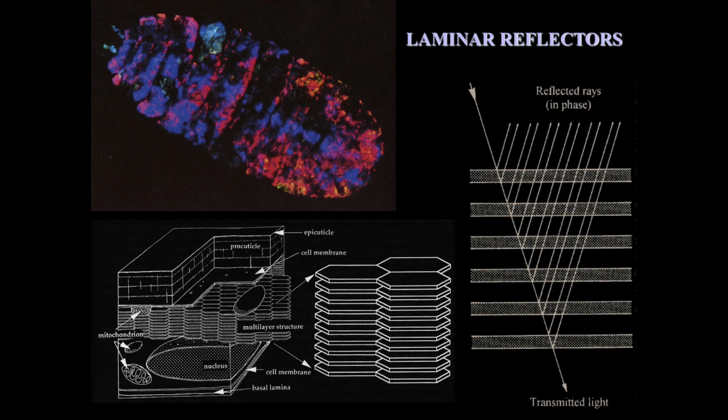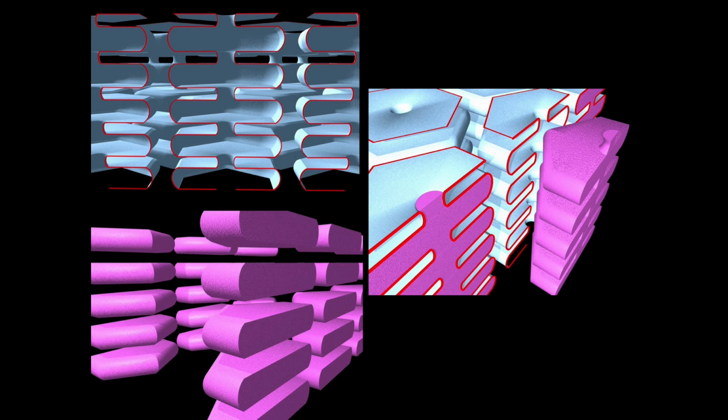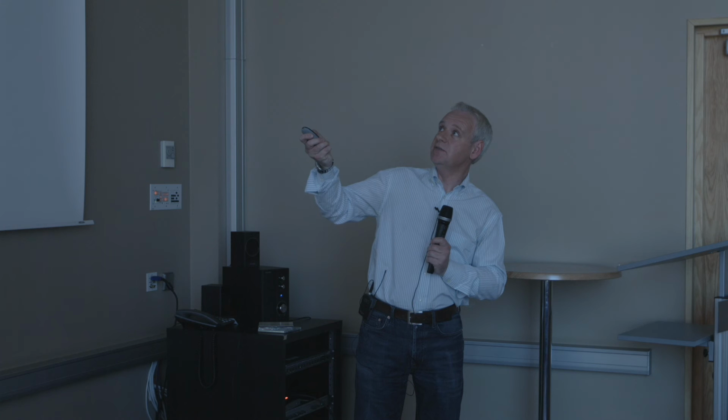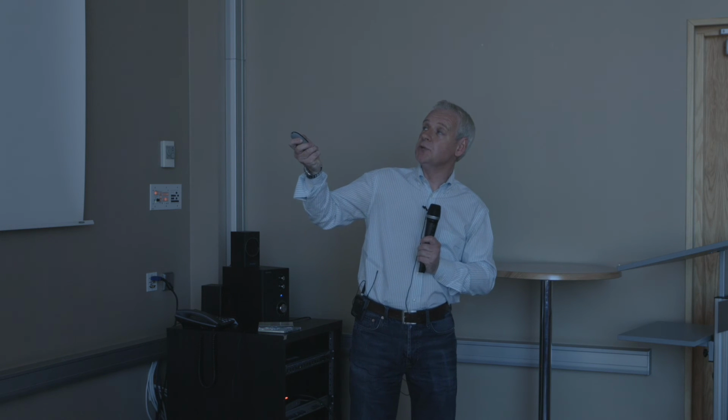So, for example, if we go back to this animal, this Sapphirina copepod, and consider that reflector, we then look inside the cell and we find the smooth endoplasmic reticulum looks like this. So it's very easy suddenly to make this device. You seed a crystal of guanine inside each of these compartments, and the crystal grows to the edges of the compartments, and that's it. So it acts as a nice mould to make these reflectors.